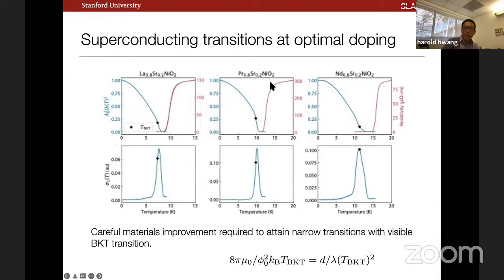After some materials effort that I alluded to, we're now in a regime where we can start to see signs of a bit of a BKT-like discontinuous jump. So BKT temperatures are estimated by these circles here, and we see a reasonably clean peak in the dissipative channel as well. And believe it or not, this was many years of work also just to try to get the materials to be of the fidelity to make these meaningful measurements.